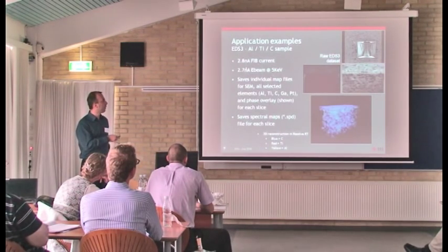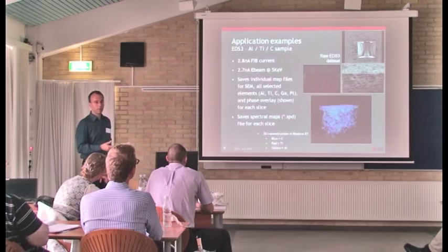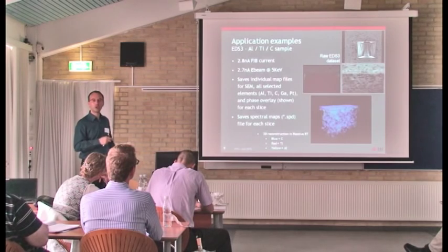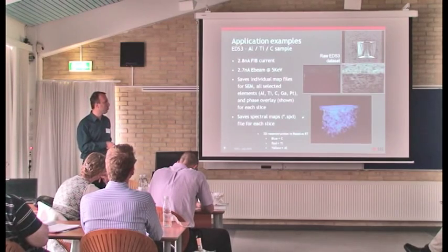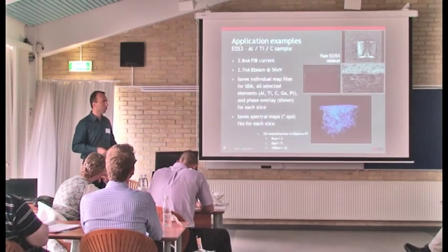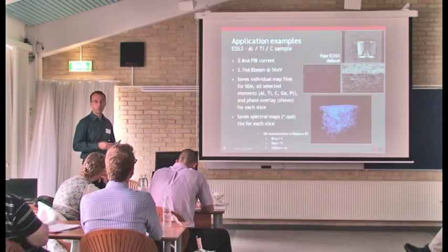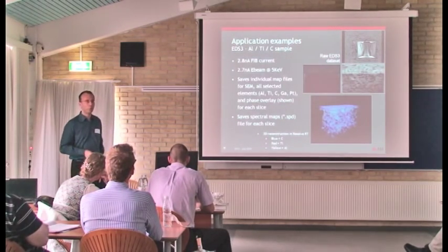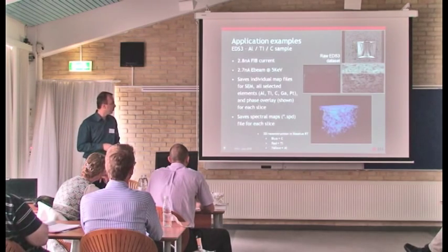At 5 kilovolt, we still have tens to hundreds of nanometers of signal that comes from the depth, which should be taken into account when generating the data. At this point, it's not so meaningful to collect slices at steps of 10 nanometers when your information comes from much deeper than that.